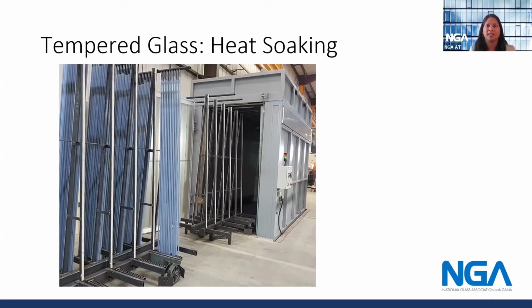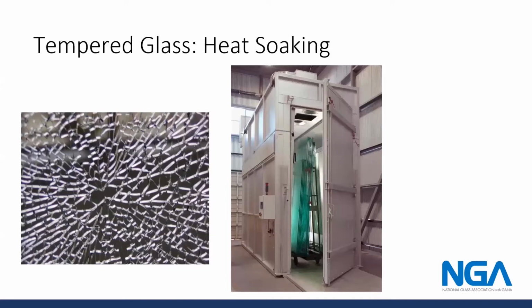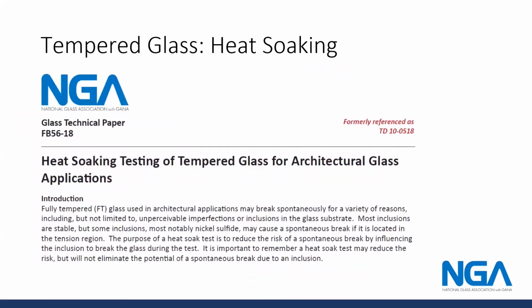The idea of heat soaking glass is that if there is going to be some type of spontaneous breakage due to inclusions in the glass, it will break during the process instead of on the site. As you can see on the screen, you have some photos of an actual inclusion with some breakage of the tempered glass, and then you have the oven of how it's being used as well. So that's all about heat soaking. In addition, NGA also has a heat soak technical paper that's on your screen. It talks about the different types of heat soaking, when you should and shouldn't heat soak, as well as some information on the actual batch process itself.